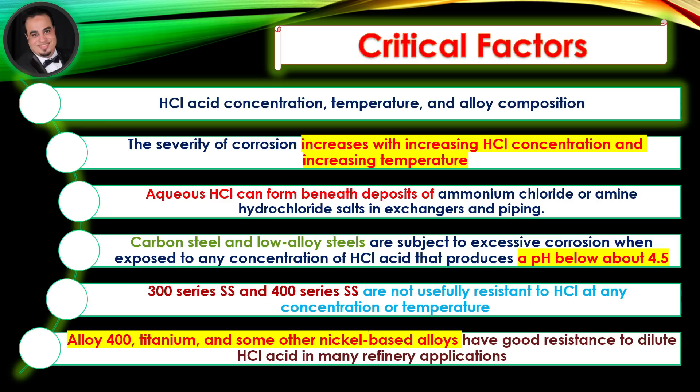300 series and 400 series stainless steel are not usefully resistant to hydrochloric acid at any concentration or temperature. Alloy 400, titanium, and some other nickel-based alloys have good resistance to dilute hydrochloric acid in many refinery applications.